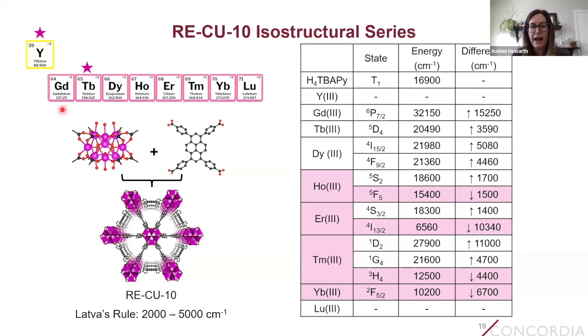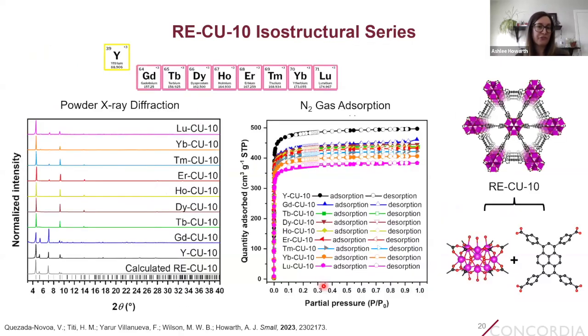And so we wanted to see what happens if we make this MOF with gadolinium through lutetium, because in some of these versions, the ones highlighted in pink here, we have the potential for that linker to metal energy transfer, or the potential for that competitive pathway. And so the first thing, of course, was Victor had to make all of these MOFs. So these are just the powder X-ray diffraction patterns that show that the materials are crystalline, phase pure, and isostructural. They're also all permanently porous, where we have these nice type 1 nitrogen gas adsorption isotherms and BET areas ranging from 1,500 to 1,900 meters squared per gram.